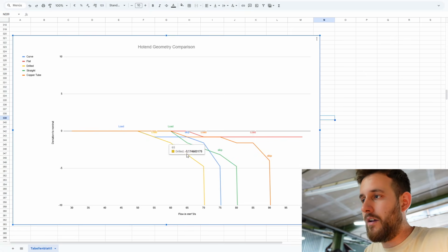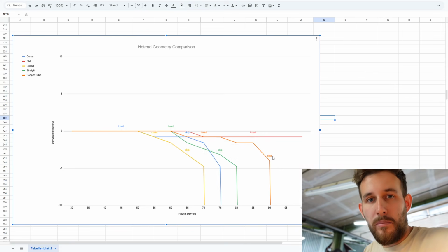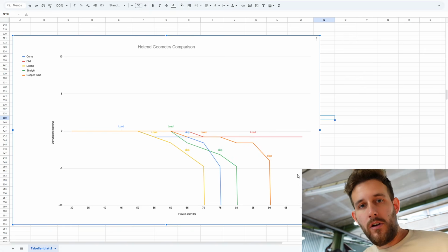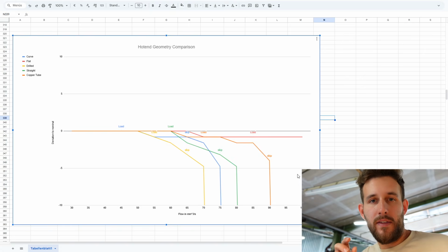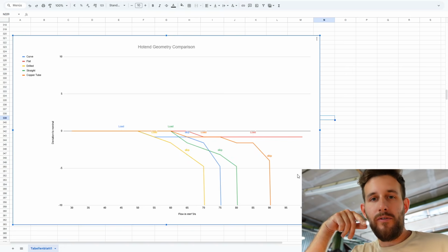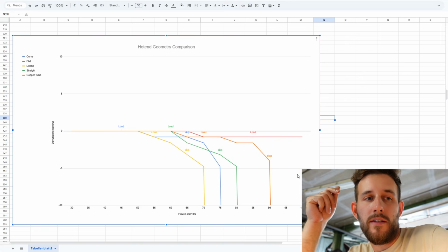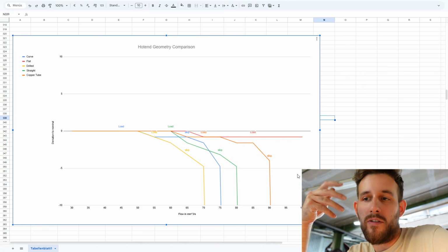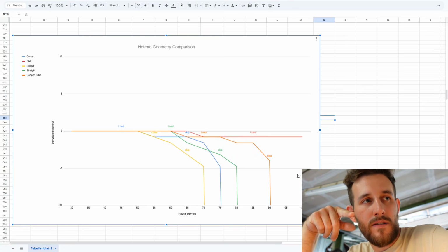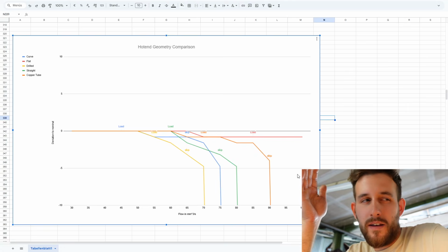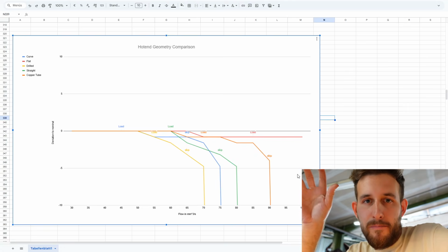But what we can take away here is that a drilled aluminum piece is skipping at 65 cubic millimeters a second. A SLM printed straight line of the same length is skipping at around 75, and a pure drawn copper tube of high quality is skipping at 90 cubic millimeters. What I don't know at this minute is how much this is affected by the missing nickel plating. I know from the experience from my Minuteman hot end that it did make a big difference, but just in long-term use. I didn't think that for the initial testing this would make a difference, but maybe it does. So let's just derive ballpark numbers from here.